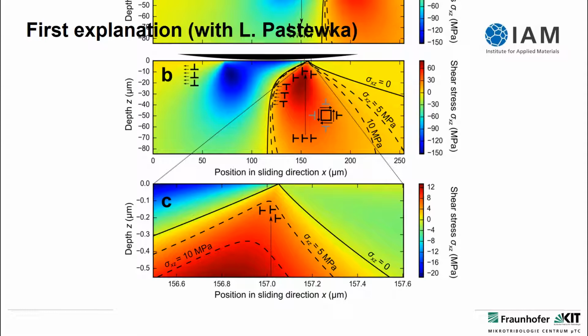The other thing we really want to examine, and are currently working on, is what is the 3D structure of this dislocation traceline phenomenon? One has to keep in mind that when you cut a TEM lamella, due to image forces you might actually lose certain dislocations, because during the thinning process image forces might suck them out of the material. That's why we're now also working on the three-dimensional structure of this phenomenon, and it might be a little bit more complicated compared to what we see just in those cross-sections along the sliding direction.